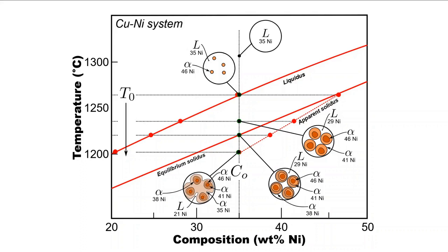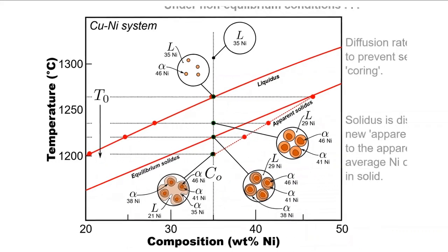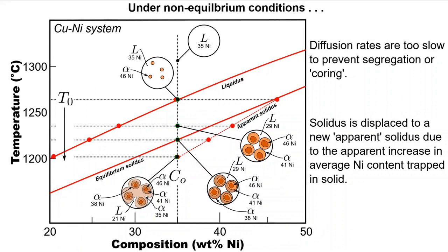Nucleation occurs as before with some enriched alpha. As we proceed with our solidification, our alpha evolves to maintain this enriched core of nickel, surrounded by a region with slightly less nickel, but still more than what we would have found for equilibrium conditions. Note that the morphology does not assume a discretized form like I've drawn here, but a smooth continuous function of decreasing nickel from the center to the outside of each grain. This carries on until the material is completely solidified, but the next thing to note is that the freezing point has decreased as well. This shift in distribution of nickel across the solidifying grains has shifted the equilibrium solidus down, as the local compositional changes affects the Gibbs free energy. The reason for this change in solidus is that the diffusion rates are too slow to prevent segregation, or trapping of nickel in the centers of the grain during initial solidification.